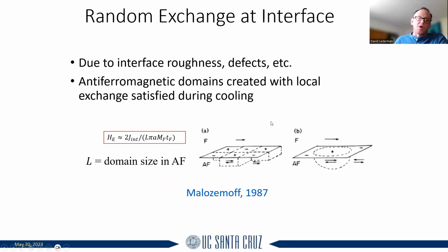So there were several models that have been proposed over the years. There's a model in the 80s by Malozemoff, where he came up with a model where you have a random exchange with the surface due to disorder, and so locally you would form domains where the net exchange would be non-zero, and locally the antiferromagnet would adjust to the ferromagnet structure as you cool down through the transition temperature of the antiferromagnet, so that you would end up having local exchange. And then at low temperatures, the antiferromagnet would freeze, and then you couldn't reverse it.